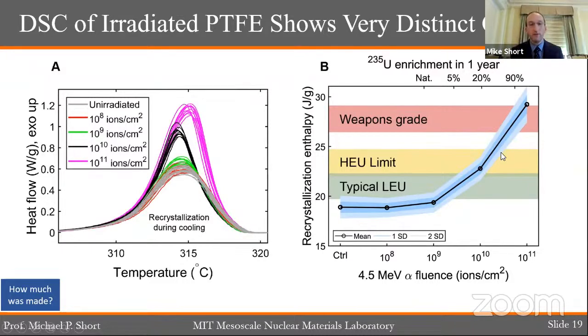For example, if we were to find a facility that had processed 10 kilos or one weapon's worth of uranium hexafluoride, we can tell the difference between low enriched uranium, something that's safe to use as peaceful reactor fuel, and what's called the HEU or high enriched uranium limit. This is about 20% enrichment, and it's a safeguard set by the international community to say you're not allowed to enrich past this level, because once you get there, it's easy to take that 20% uranium and enrich it further to 90% to make a weapon. We can tell that difference to pretty high confidence, approaching about 99% confidence.